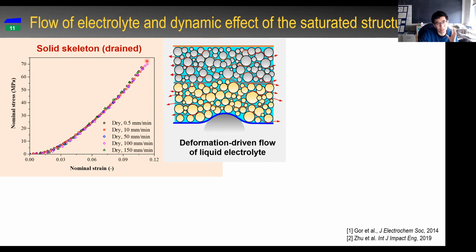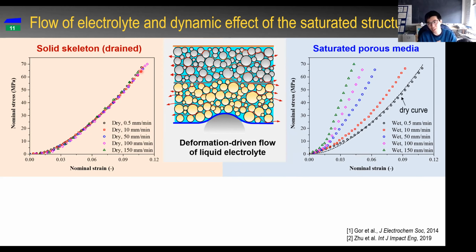We can see the dry material, where the curves are almost identical. That means there is no contribution from the electrolyte. However, if we do a saturated porous media with electrolyte, we see clearly there is a strain rate effect, or speed or dynamic effect. And we put the dry curve here. That means at a very low speed, the dry and the wet curve are the same.